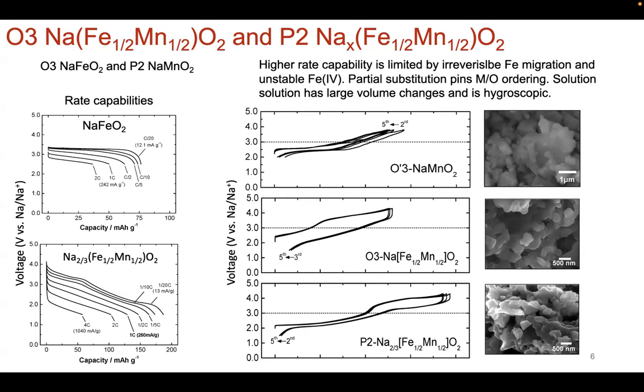Okay, so you could see that here for sodium 2/3. So here you're not achieving stoichiometric ratios. So you have to have 2/3 of sodium ions in this layered cathode material. But at 4C, you're achieving a little bit over 50 milliamp hours per gram, whereas for the end members like sodium iron oxide, already at 2C, you're achieving 30 something milliamp hours per gram. Okay, so the higher rate capability is really limited by the fact that having iron there will pin the metal oxygen ordering.